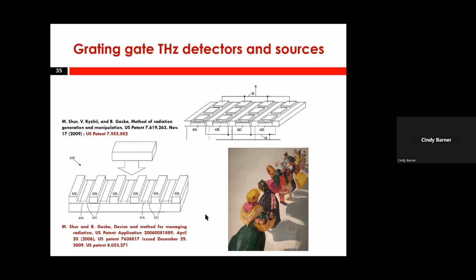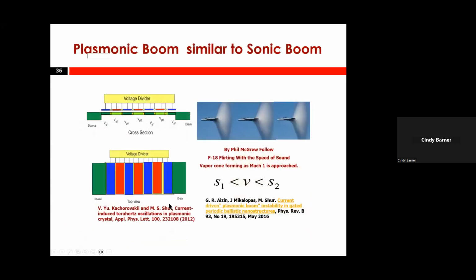There is another interesting mechanism too, which is trying to have effects similar to a sonic boom. One of these pictures is actually a picture of an F-18 crossing the sound barrier. But what I did, I showed several of such events because in a plasmonic device, when electrons cross the plasma velocity barrier, when the drift velocity crosses the plasma velocity barrier, that could be repeated hundreds if not a thousand times. And the power could be very, very large. Now, what is very important, we saw that there is new physics. Now, this new physics must directly go into the design of terahertz electronics, of terahertz devices, integrated circuits.